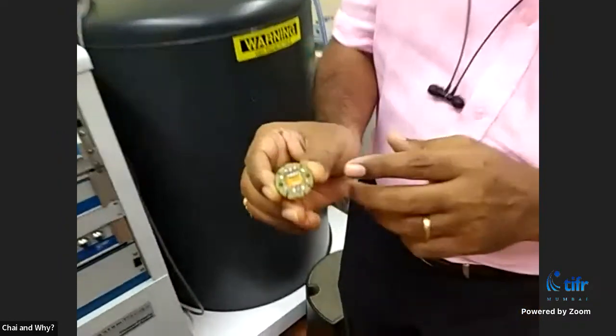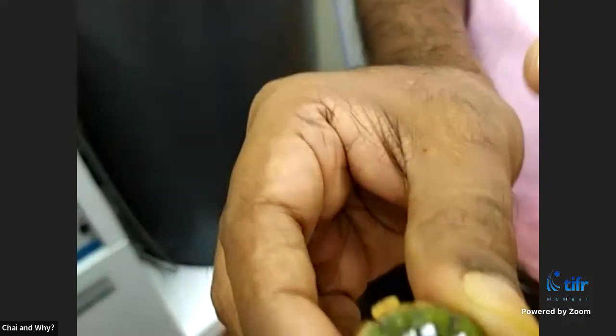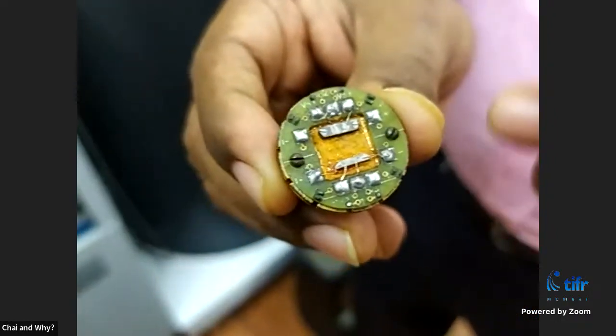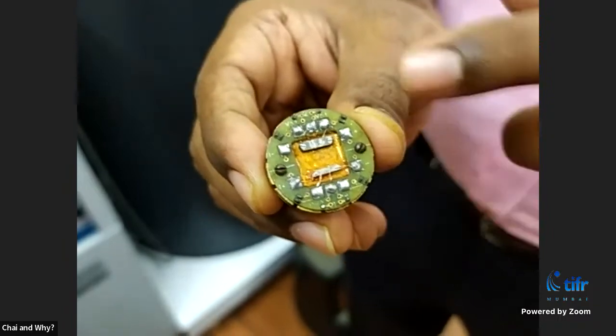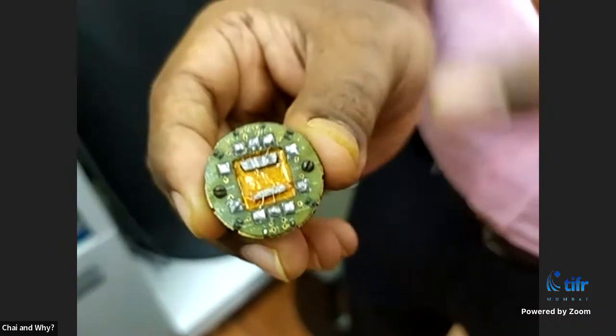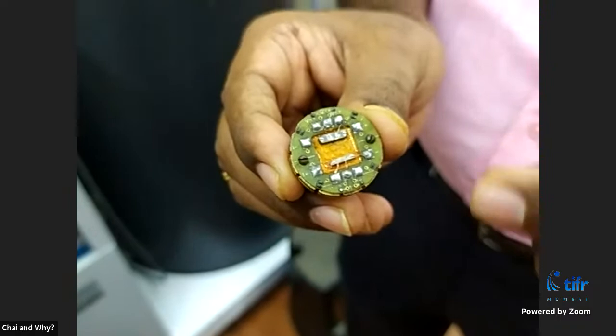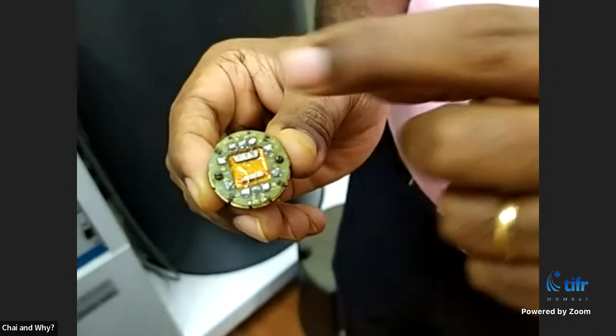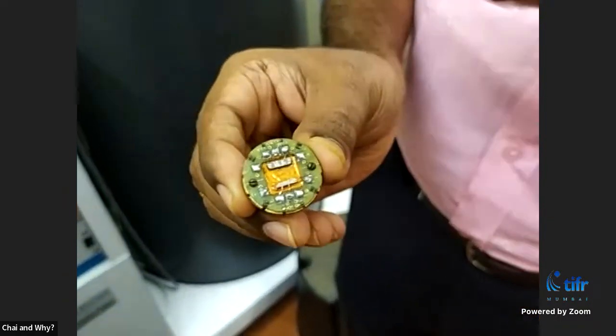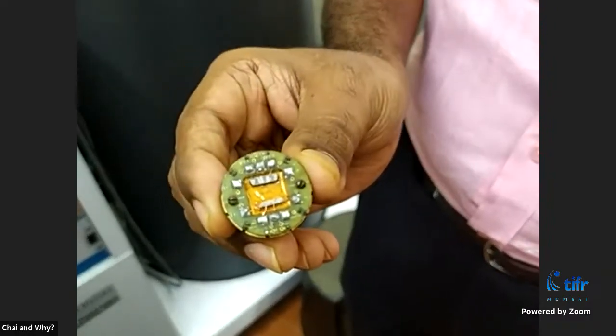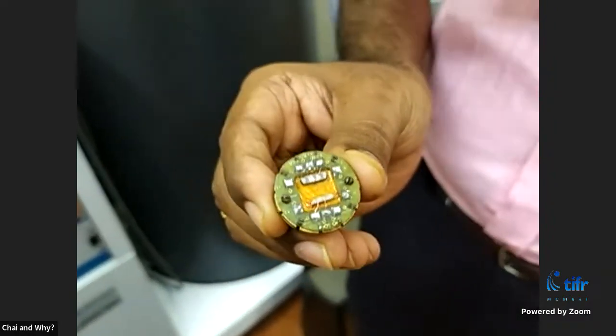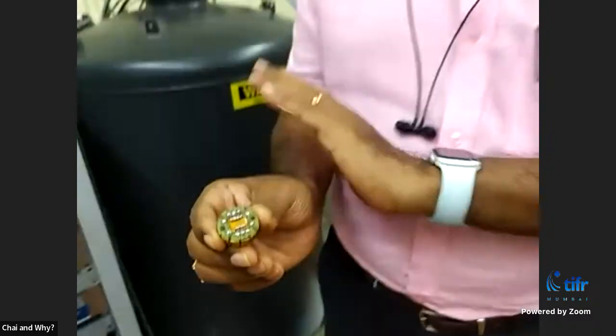So this is how the samples are. This is to measure the electrical resistivity. We have 2 different samples along 2 different crystallographic directions. We make 4 probe contacts. The current is passing through the sample and coming out on the other side, and in between, we are measuring the potential difference, that means the voltage. From this, we can measure the electrical resistance of the sample.